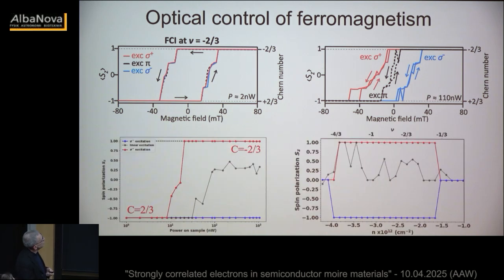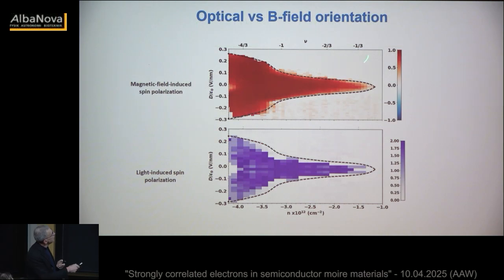And this again, we looked at the power dependence. We first initialized using magnetic field and tuned the magnetic field to 0, in the C equals 2/3 state. And with sigma plus, we were able to switch it completely to C equals -2/3. With sigma minus, nothing changed. And this is the doping range over which this works, almost covering exactly the magnetic field.